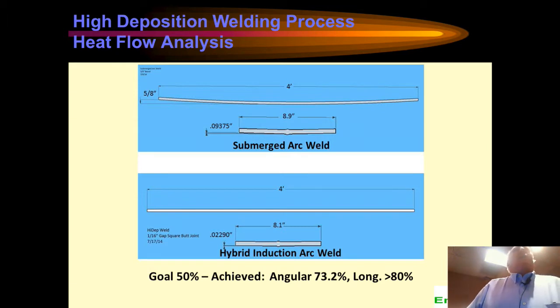Yes? Based on the gas content that you had for your torch, which was 90% argon, 10% CO2, have you ever thought about doing tri-gas for higher heat application? The most important thing is we have a fairly large liquid pool. We don't want it sloshing around, so we need a very stable spray transfer. With the metal core wires, you can go to a much higher current density and still keep a stable spray transfer. We tried several different argon CO2 mixtures, but we haven't tried any other gases.